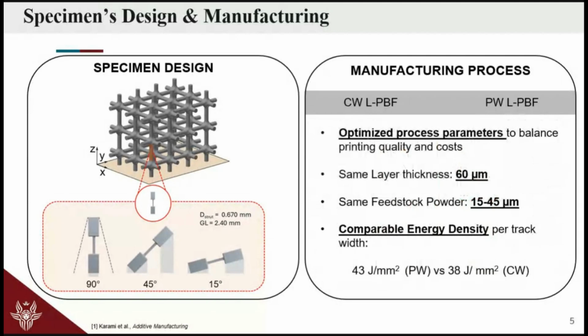Of course, if we want to have a comparison, we need to have something fixed or at least constrained in order to have the closest comparison as possible. And to do this, we decided to keep the same layer thickness, same feedstock powder, as well as comparable energy density per track width. Given this, these specimens should be considered in their as-built conditions, so no kind of post-processing treatment has been done, rather than a classical heat treatment to have either stress relieving, or the transformation change from martensitic to alpha plus beta phase.